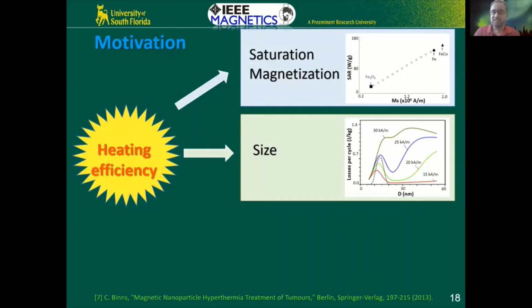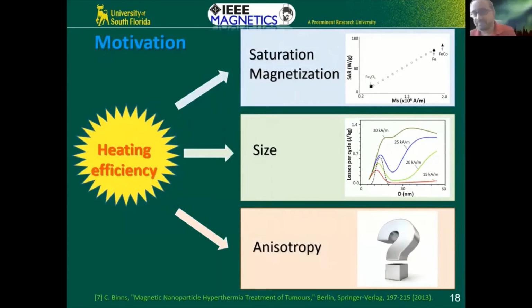Unfortunately, even though iron and iron cobalt have much higher saturation magnetization, we still have to mostly work with this and somehow improve it. That's the only thing that's allowed. I already talked about size dependence, but can we do something else? Can we change the shape of these particles? Can we change the surface structure of magnetic oxide or other kinds of particles? Can we make some kind of core shell structures, some kind of hybrid geometry where you have a core and a shell of different materials, and you can have exchange interaction or exchange anisotropy between the core and the shell?